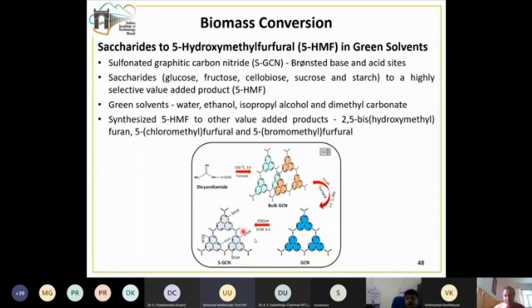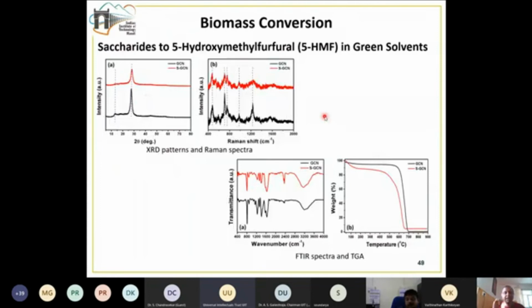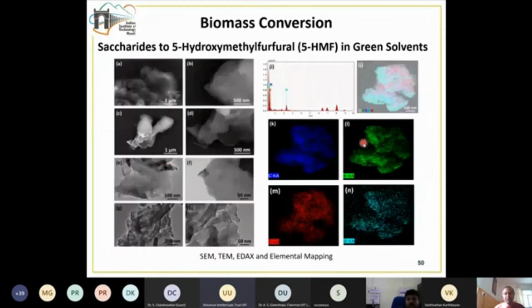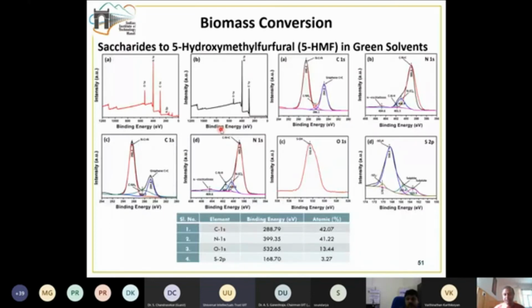First we synthesized this material using a high temperature furnace, and further functionalization was done using chlorosulfonic acid. Then, similar to the previous work, we did a detailed material characterization study using X-ray diffraction and Raman spectra. The sulfonyl functionalization was studied using FTIR, and the thermal stability of the material was studied using TGA. Then the morphology was studied using SEM and TEM, which indicated a sheet type of morphology. Further information was obtained from elemental mapping. Then we did a detailed XPS characterization to understand the structure and interactions better, and we were also able to figure out how much sulfur is present in the sample due to the functionalization.